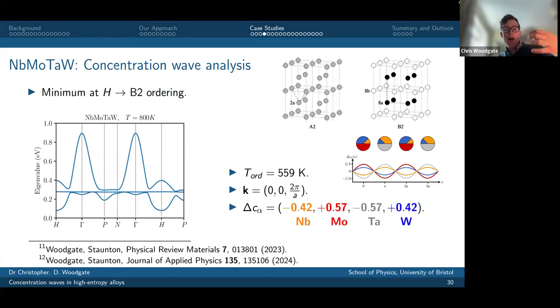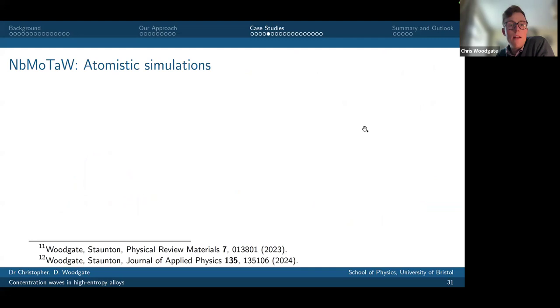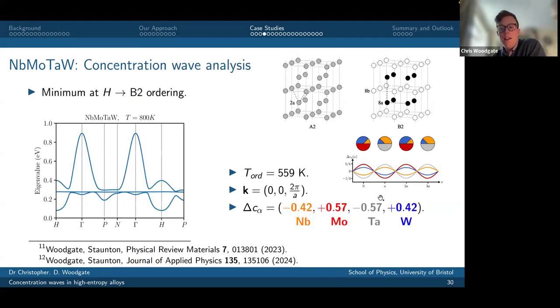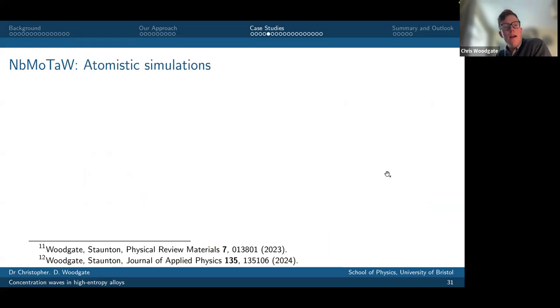So an element like niobium or tantalum, which has one fewer valence electron, would prefer to be surrounded by the elements molybdenum and tungsten, which have one more valence electron than it. Okay, so fine. And I've got a little cartoon of what that concentration wave looks like in one dimension here. Okay, but I can go further.